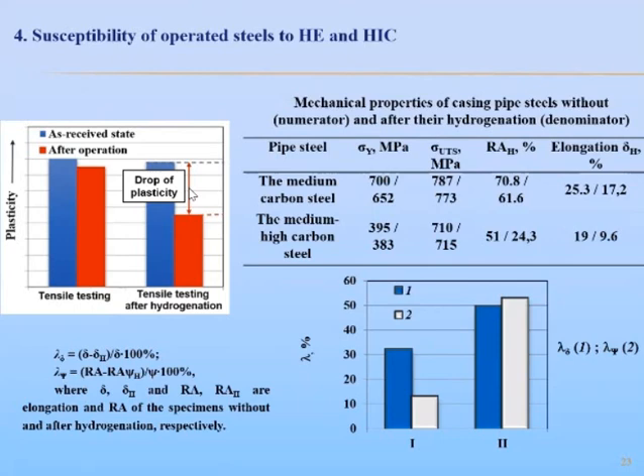Susceptibility of steels to hydrogen embrittlement can be studied by tension of specimens in air after their hydrogen precharging electrolytically. The plasticity characteristics of steels without and after hydrogenation are compared, and susceptibility of steels to hydrogen embrittlement can be evaluated by the change in plasticity characteristics. And also here you can see research results demonstrated that both studied steels of casing pipes were sensitive to hydrogen embrittlement.